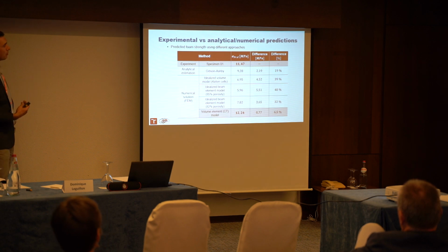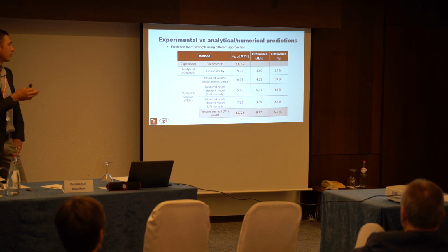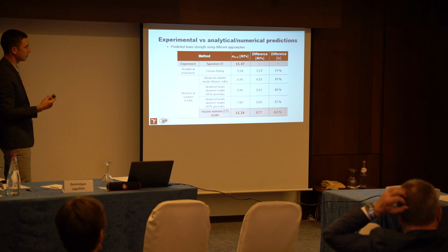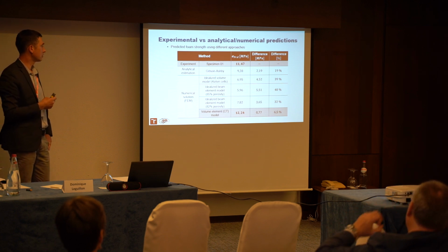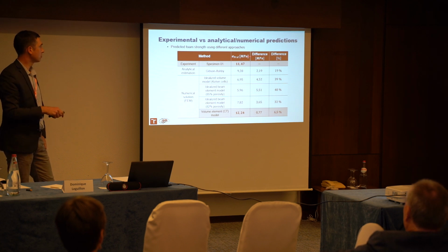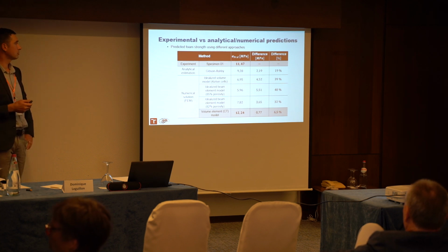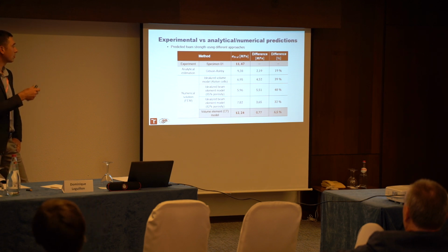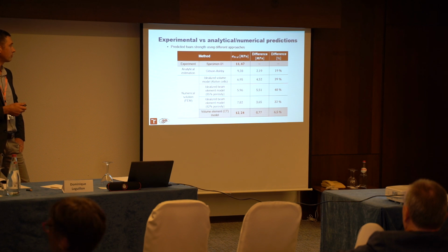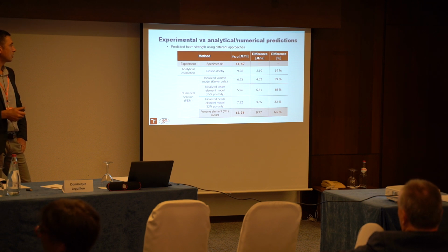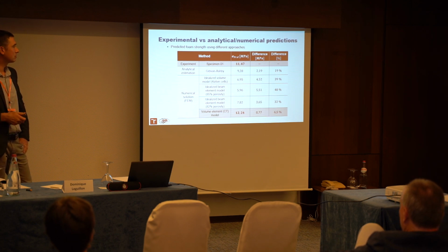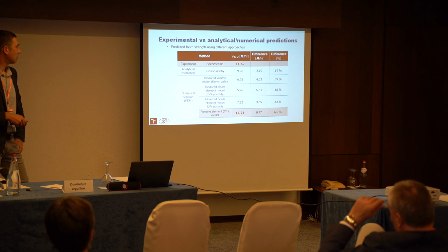So we compare different approaches and how we can predict the strength of the foam using different approaches, including this which I present today. So in the experiment we measured fracture stress about 11.5 megapascals. Then we tried to analytically estimate using these Gibson-Ashby relations. Here we had a difference around 19-20%.